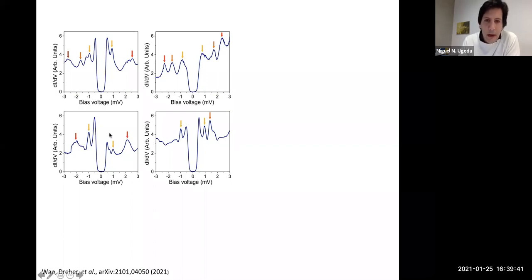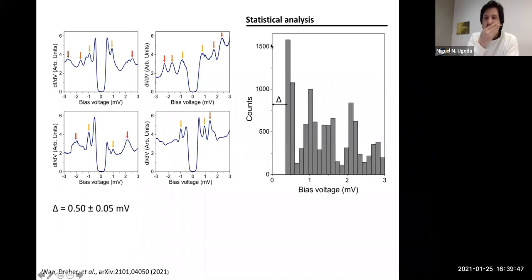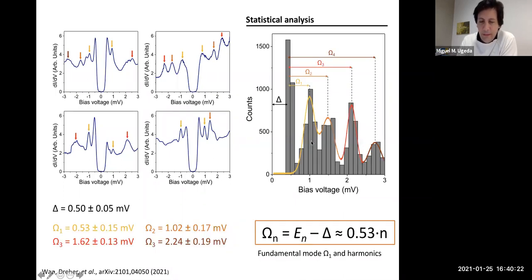So in order to put some numbers and learn something about it, we did some statistical analysis of the peaks that we found in our curves. For this particular statistical analysis, we have used, I think, nearly 3,000 curves in hundreds of different places. And we find clearly five peaks, 1, 2, 3, 4, and 5. The first one corresponds clearly to the superconducting coherence peaks and yields a value of half a millivolt. And the other four can be fitted in this way.